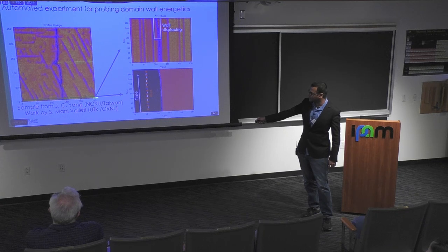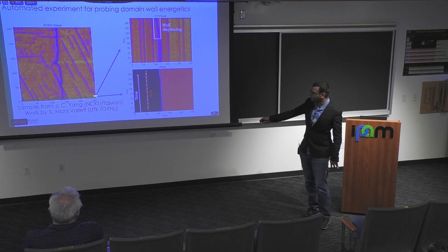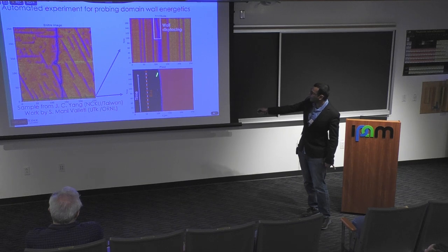In this case, this is, let's say, the third line. And what we do is we scan this same line over and over again over time. But what we're doing here is that after every three lines or so, a bias is applied. In other words, a voltage is applied at this particular domain wall, and this voltage is increasing in magnitude